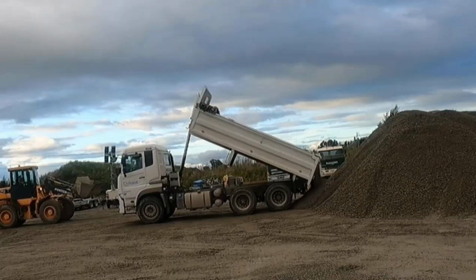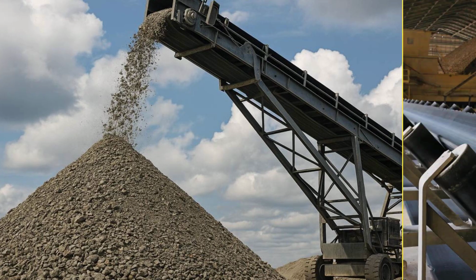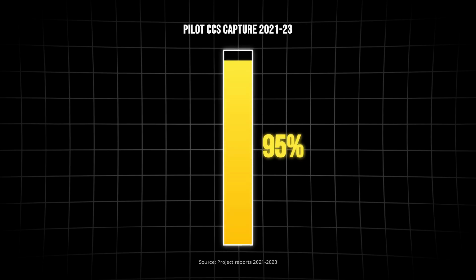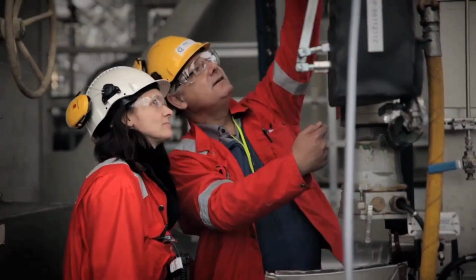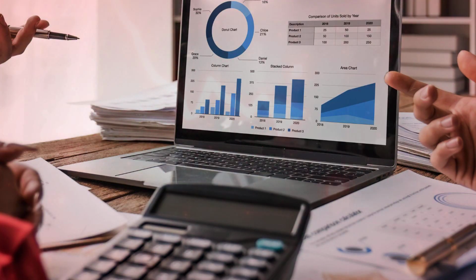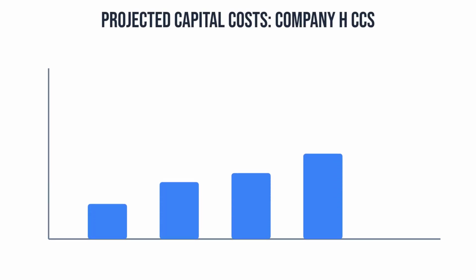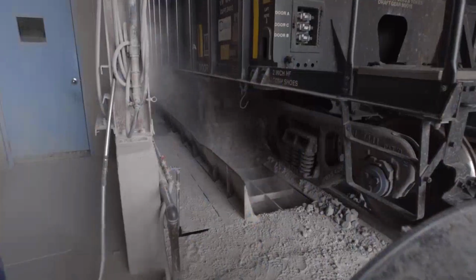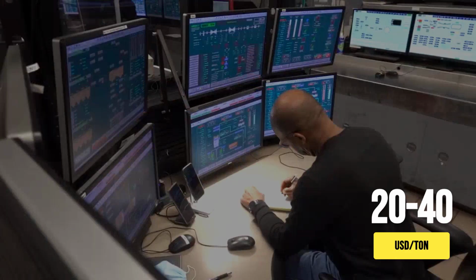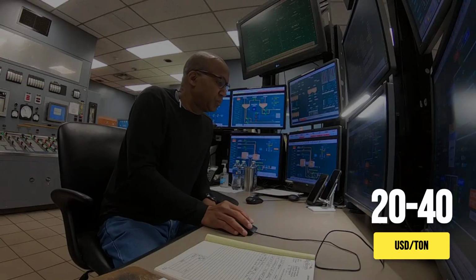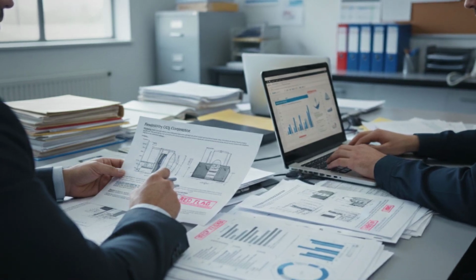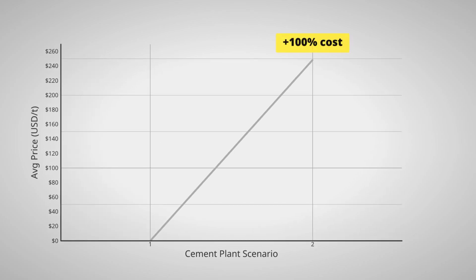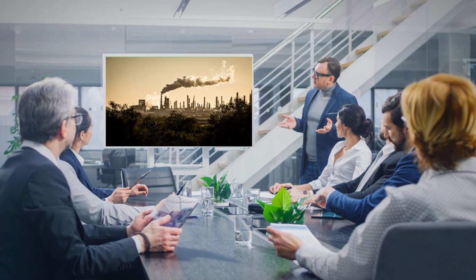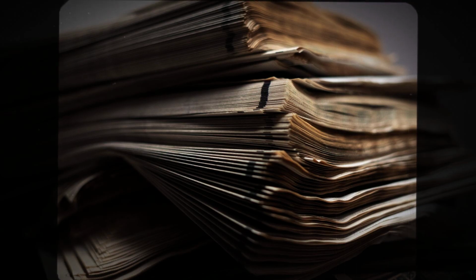Beyond supplementary cementitious materials, the industry's gaze turns to carbon capture and storage. Recent pilots in Europe and the United Kingdom have achieved over 90% kiln carbon dioxide capture using solvent or membrane systems. But the economics are daunting. At Company H's site, projected capital costs rose from $60 million to $145 million in 3 years, with annual operating expenses running $20 to $40 per ton of carbon dioxide captured. Internal audits warn that full plant carbon capture and storage could double cement prices unless backed by major policy incentives. Executive memos urge caution, noting that while technical feasibility is proven, the business case remains fragile.